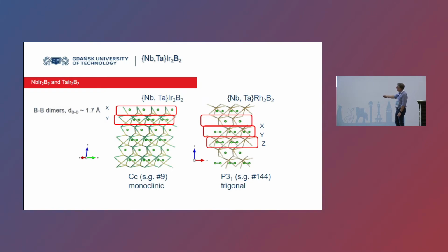And there is a link. The link is that we have a different stacking. Here is XY, here is XYZ. So either 2 stacking layers or 3. And that one is a non-centrosymmetric, monoclinic crystal structure. That one is chiral, trigonal, of course, a non-centrosymmetric crystal structure.